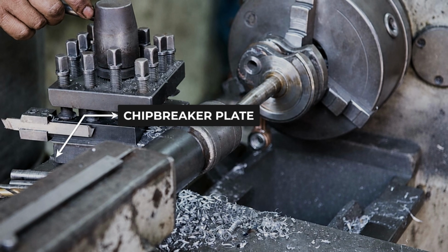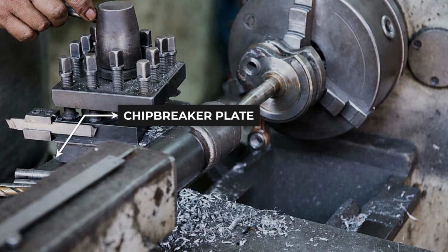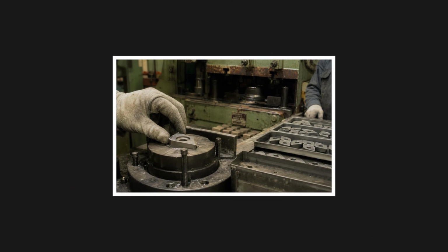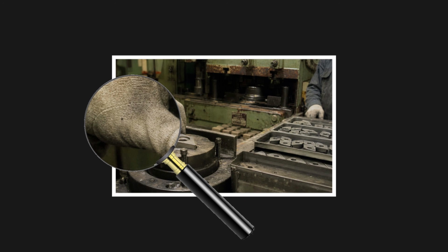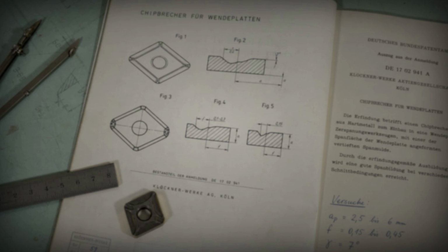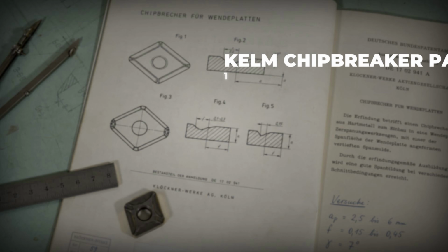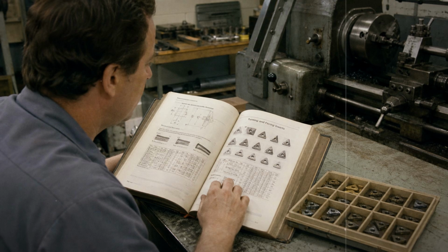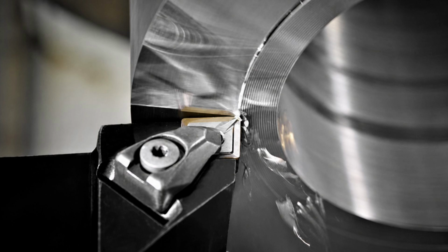Early flat-top inserts still needed a separate chip breaker plate clamped over the face. Through the 1960s and 70s, the grooves were pressed and sintered directly into the insert, with patents like Klöckner's in 1967 marking the shift, and chip control became something you order from a catalog instead of grinding by hand. The groove did double duty.